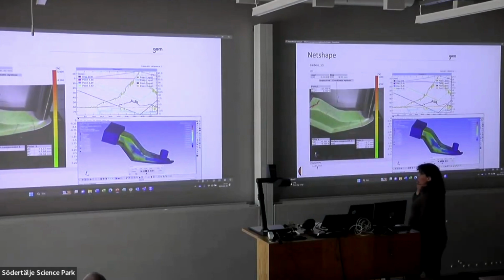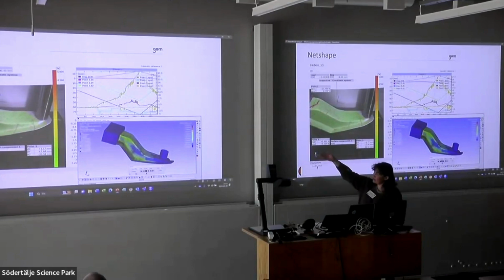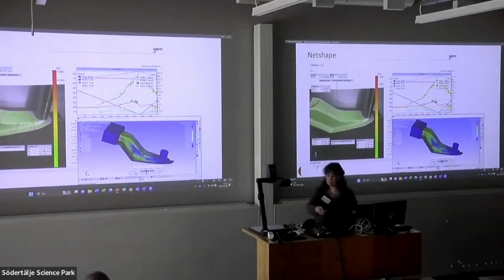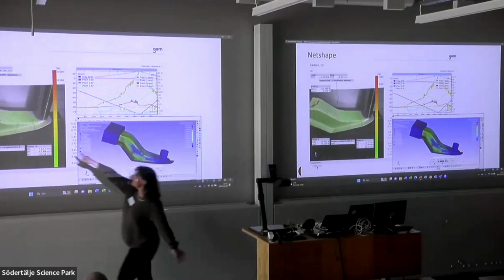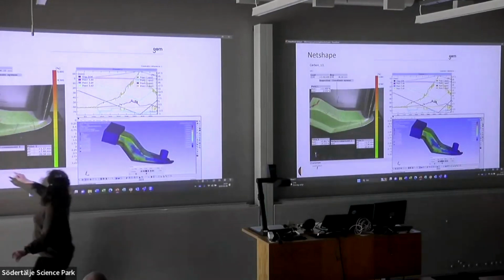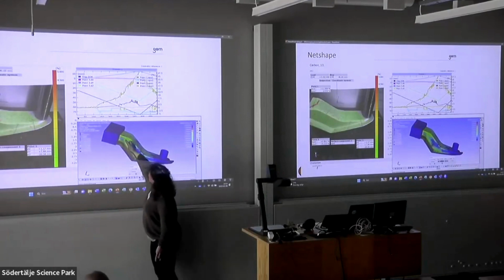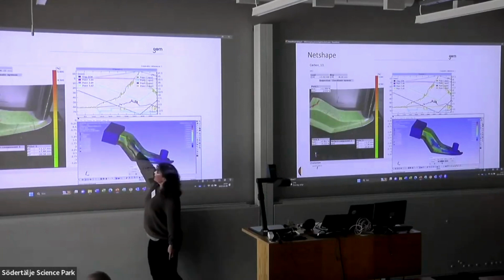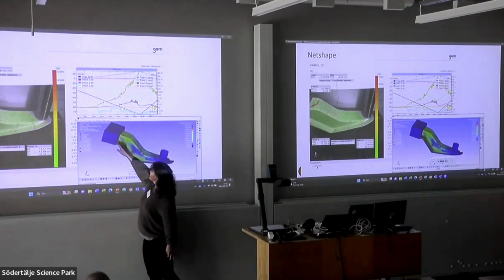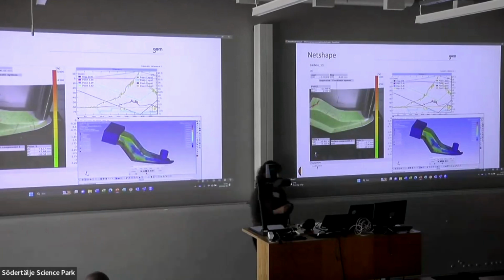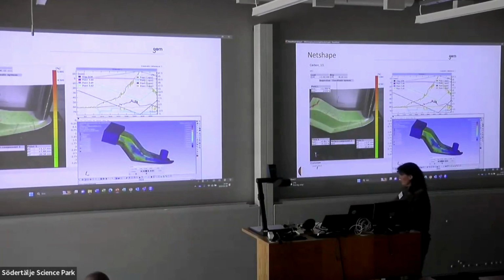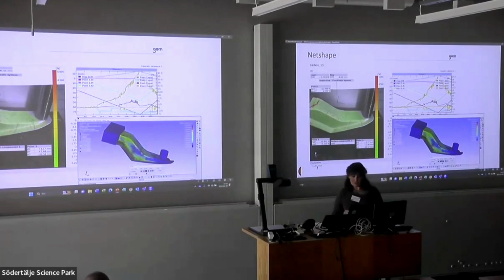And what we can see here is the crack at the top. Pointer's not working. There we go. So here we have the crack being here, and we do see that there is a high level of stress at this point, but there's probably a higher level of stress at that point. In some cases, some of them broke up here and some of them broke up here. So we're not too bad in where we're predicting the highest amount of stress is going to be.